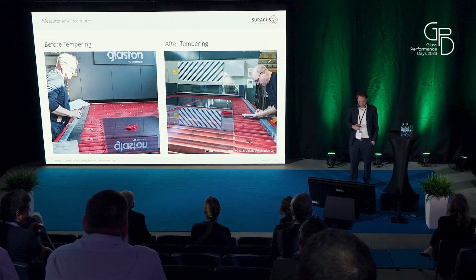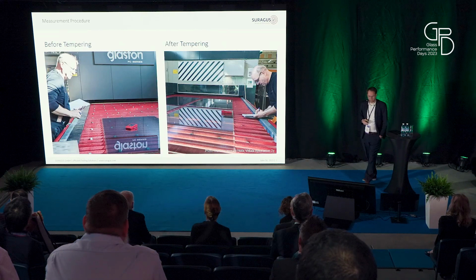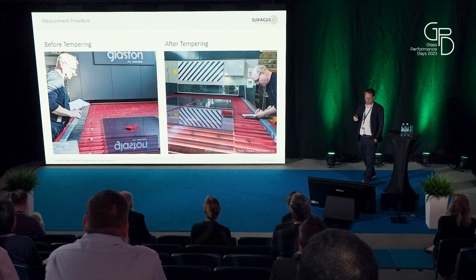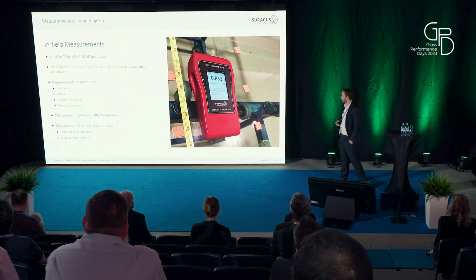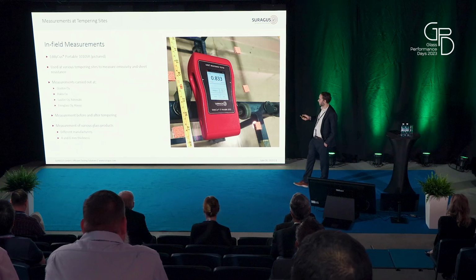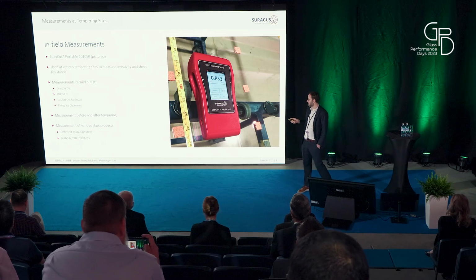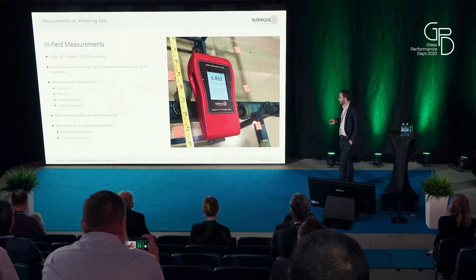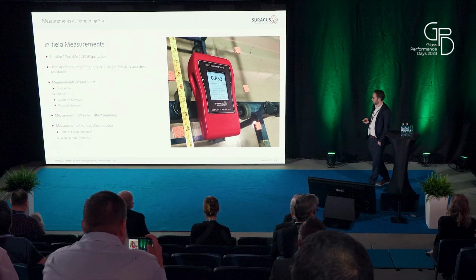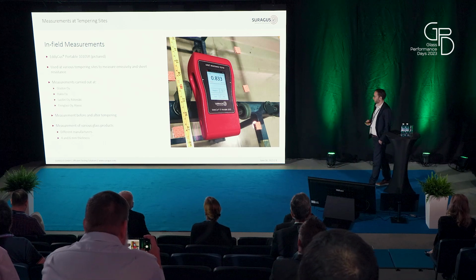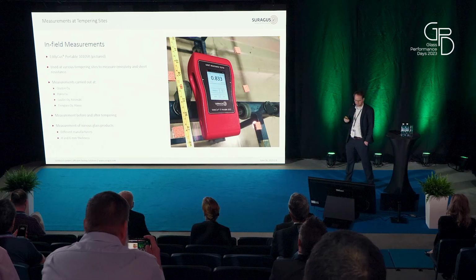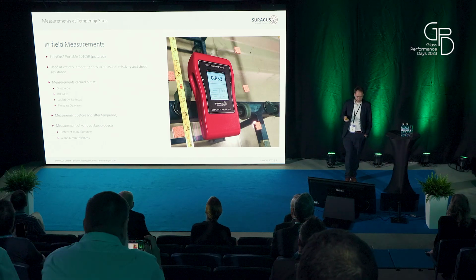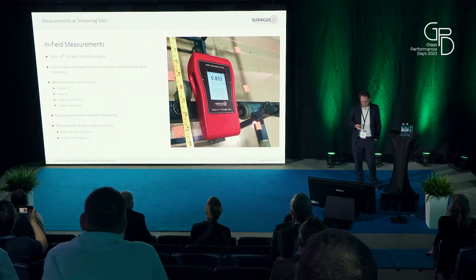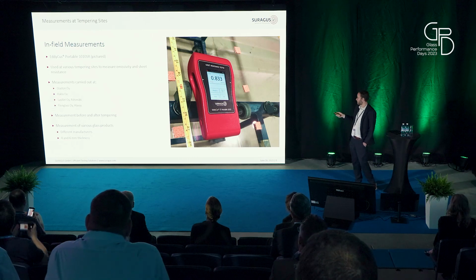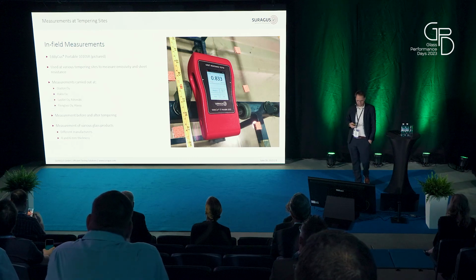We did measurements before the tempering and after the tempering, and we ran this through different glasses at different measurements carried out at different sites here in Finland mainly. And we observed different glass. We measured different glass thicknesses, different glass manufacturers, and used different furnaces. And the measurement was done with a portable device, which is a handheld device to measure the emissivity.